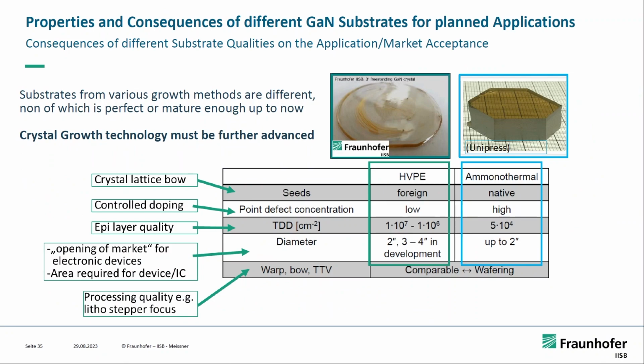So what you would really need to launch a technology is a larger crystal at decent cost. If you compare both, you have from ammonothermal and from HVPE substrates, different properties. And this is why you see these differences in device performance here, even though you have gallium nitride native substrates in both cases. The threading dislocation density, or total dislocation density, is much less for the ammonothermal, by 1 to 2 orders of magnitude. The diameter is a bigger issue than with HVPE.